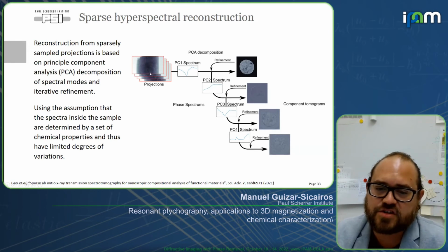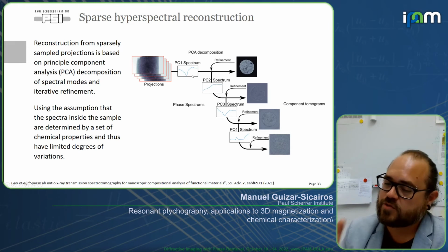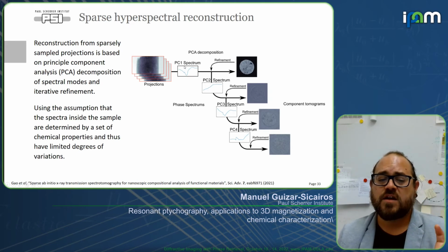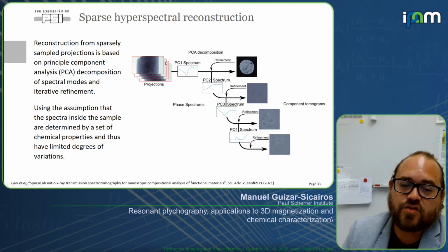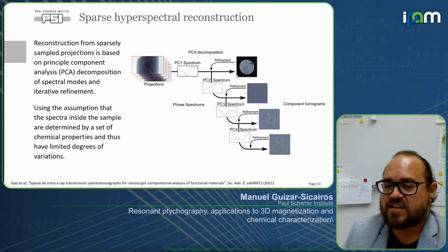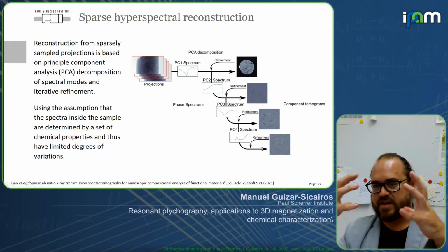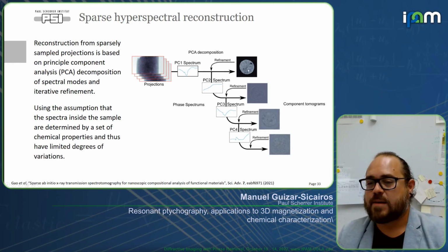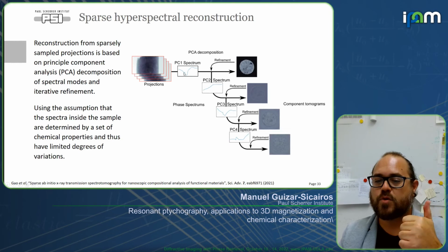So you have some projections. From these projections, you can already estimate the principal component spectral decomposition using very low resolution 3D reconstructions that are unaffected by the undersampling. Then you use the high resolution projections and an iterative algorithm to refine. First, you refine the first coefficient, a three-dimensional array that looks like the sample, where each voxel corresponds to the coefficient of the first component.